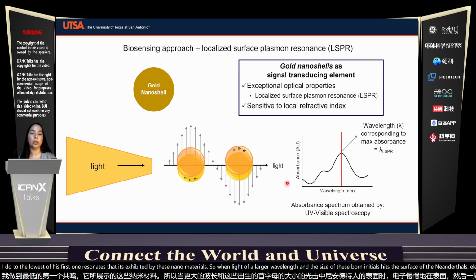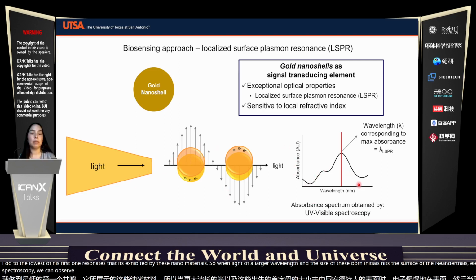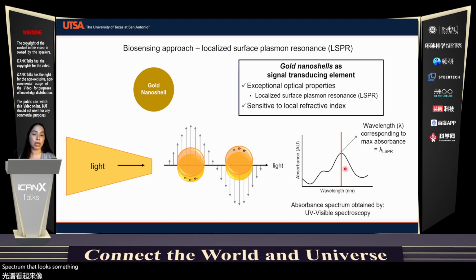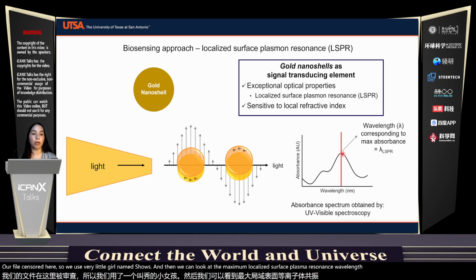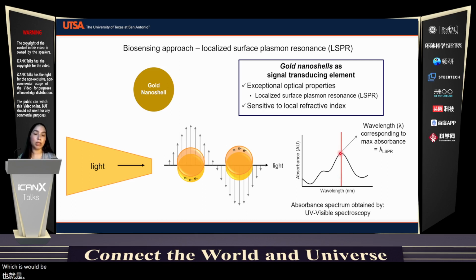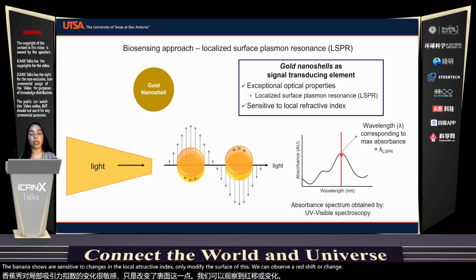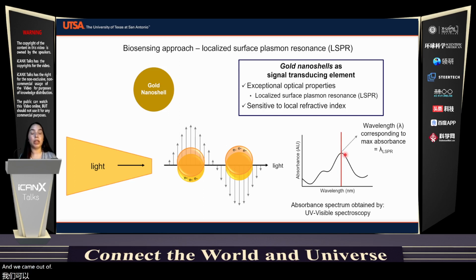And then when we use UV visible spectroscopy, we can observe a spectrum that looks something like this for the gold nanoshells that we use for our biosensor here. So we use spherical gold nanoshells, and then we can look at the maximum localized surface plasmon resonance wavelength, or max LSPR, which would be indicative of this point here. And whenever the gold nanoshells are sensitive to changes in the local refractive index, so when we modify the surface of this, we can observe a red shift, or a change to the right, and we can look at changes in surface properties that we can use to detect changes in sensitivity to different biomarkers.